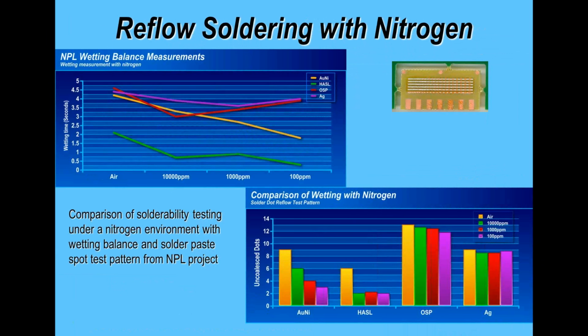Now, I wanted also to include a little bit about nitrogen in this webinar, and as I said, nitrogen has a distinct advantage that allows you to generally reflow at lower temperature. It can allow you to reflow at a faster conveyor speed, but it actually costs you money. And you have to find the sweet spot where you're getting an improvement on performance without paying a lot of money. And these are just some results from one of the NPL projects, National Physical Laboratory projects that we've run. And all I'm trying to do here is just show you graphically the wetting performance on different finishes at different nitrogen or air levels. And as you can see, when we get down to 100 ppm, yes, there is an improvement in performance, but